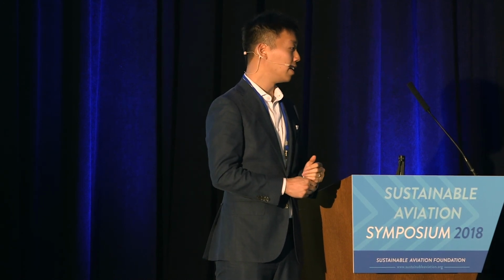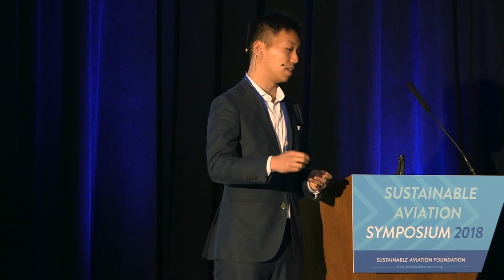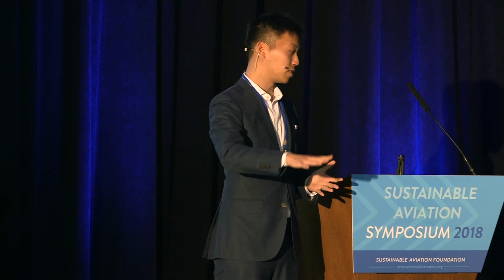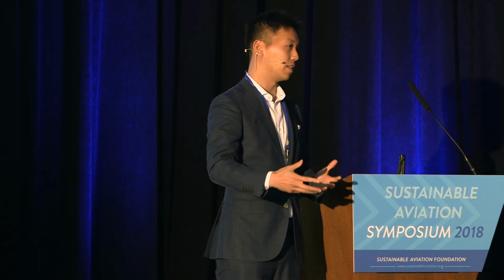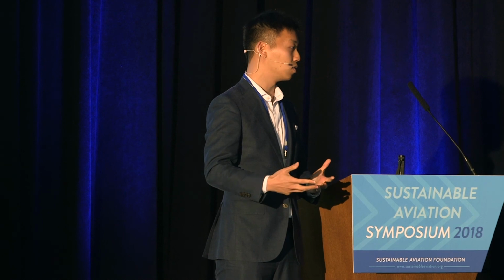Yeah, good question. It's very much a hyped up technology in the battery world. It does have its uses, but perhaps not quite as remarkable as people are imagining. So right now, the most interesting use case for graphene is as essentially a conductive additive to improve the electronic conductivity of your electrode materials. And why that's important is ultimately the electronic pathways created by graphene are much more conductive than the current types of synthetic graphite they use as additives.